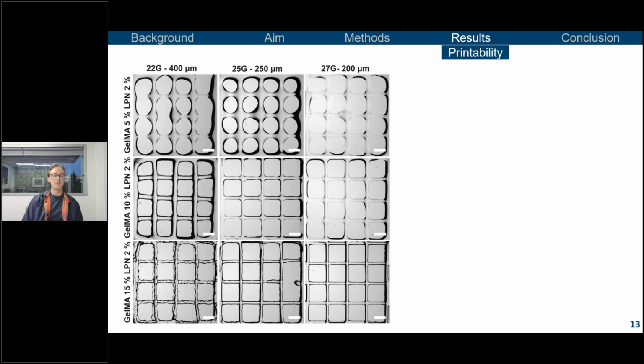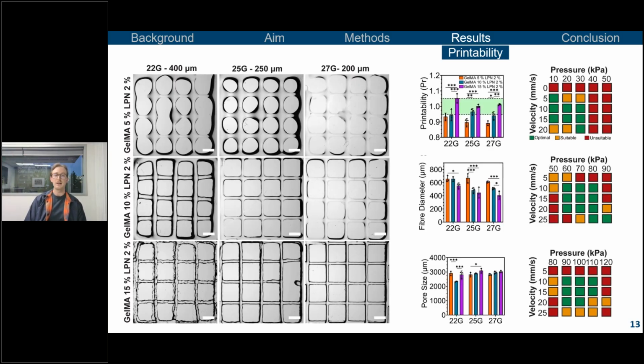We then looked at printability and different pore and fiber structures at different concentrations of GelMA 5 to 15% and different nozzle sizes ranging from 22 to 27 gauge, where we assessed the printability index, the Pr value, so the squareness of these pores, the fiber diameters and the pore sizes. We're able to show that different velocities and pressures induce different results and there was an optimal range within the different GelMA concentrations, and that the 27 gauge nozzle was the most optimal nozzle, resulting in decreased fiber diameter, optimal printability index, and pore sizes.